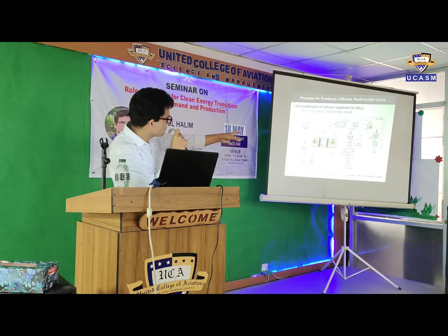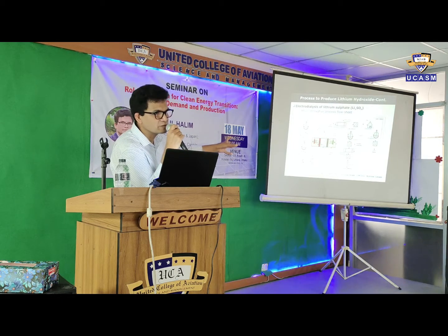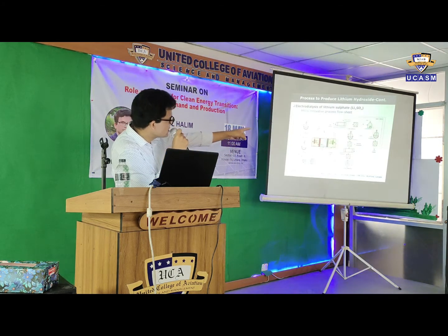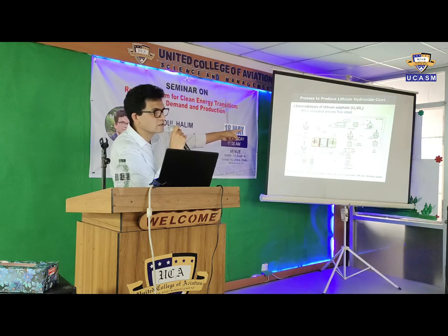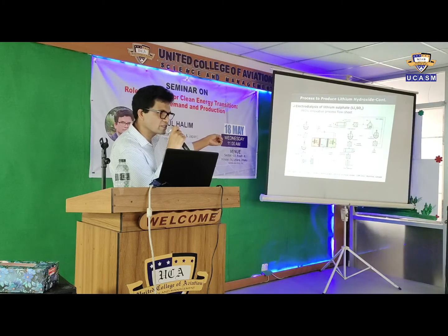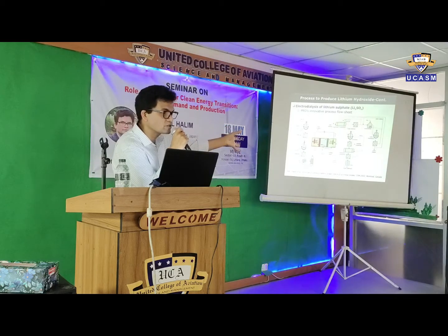What is the difference in this flow sheet compared to the others? The electrochemical membrane system is very similar, only with the integration with the other part, with this one. So we start from hard rock, spodumene, we produce lithium sulfate, we remove the impurities, we remove the remaining calcium and magnesium by introducing ion exchange technology. Then we feed to the membrane technology to produce sulfuric acid and lithium hydroxide.